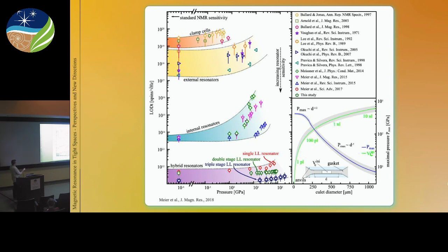And the good thing about that is that at ambient conditions, it's actually perfect. We are able to increase sensitivity by approximately 4 orders of magnitude, which is nice. But unfortunately, as you can imagine, having the coil directly between the diamonds is not so good for the coil itself, because the coil basically ceases to be a coil even within approximately 5 GPa of pressure, which is the reason for these strongly deteriorating sensitivities here within each experimental run.